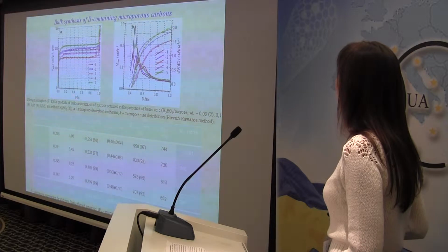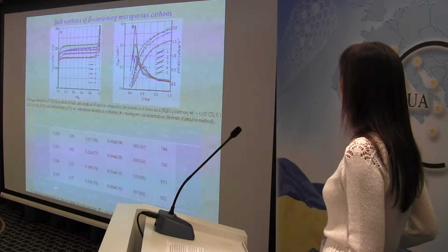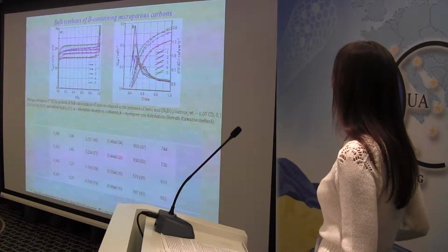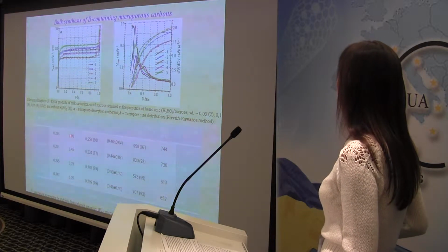Under similar conditions, at a temperature of 900 degrees, bulk carbonization of sucrose in the presence of boric acid leads to the formation of microporous boron-containing carbon materials. Micropore volume is up to 0.3 cubic centimeter per gram. At the same time, with increasing boron content, a decrease of micropore uniformity with increasing size is observed, and the potential of nitrogen adsorption decreases from about 4 to 3.2 kilojoule per mole.